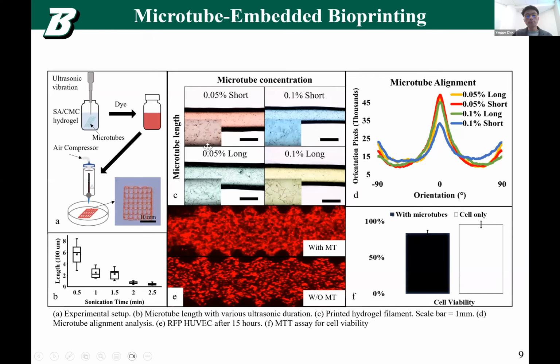And then we blend them into the bioprinting hydrogel and bioprint the filament to try if the microtube is long, if the microtube is short, if the microtube concentration in the hydrogel is high, which is 0.1%, it's pretty high already based on our test, and if it's low, which is 0.05%. And then we test the alignment of microtubes within the hydrogel when we print it out.